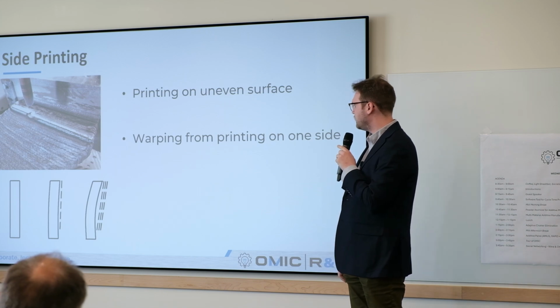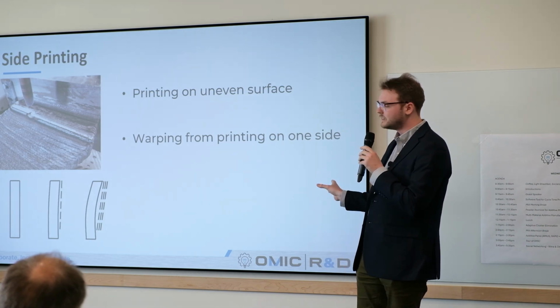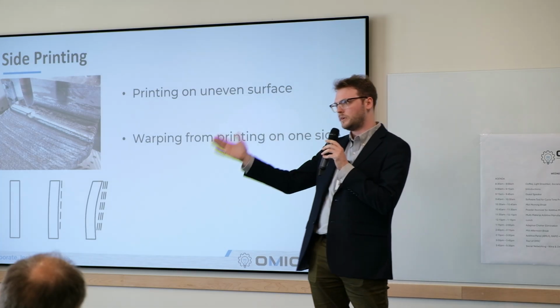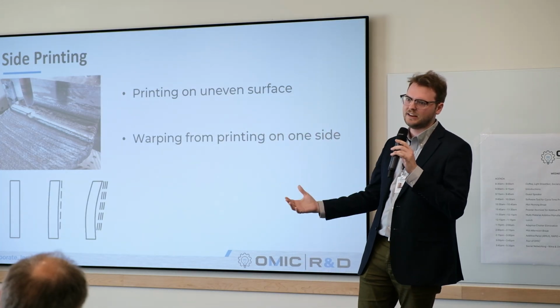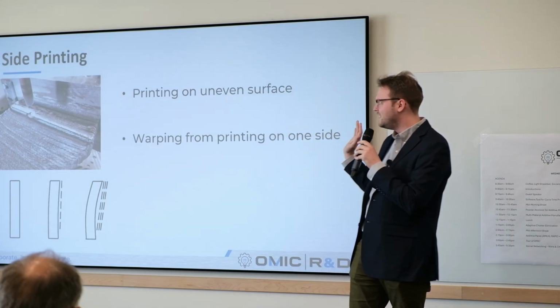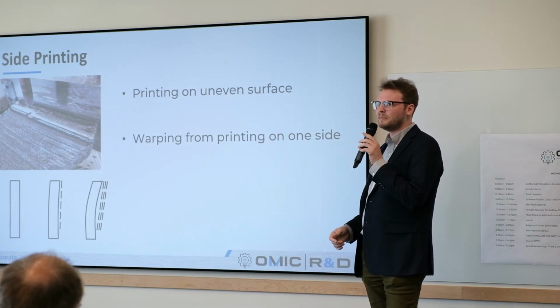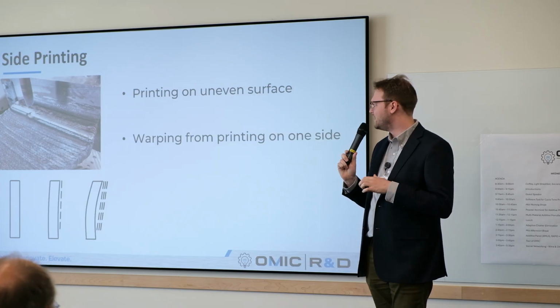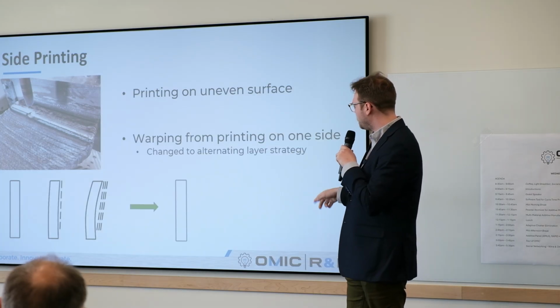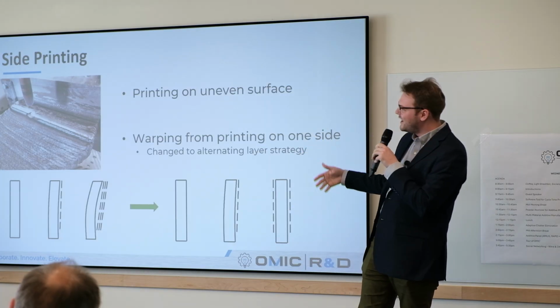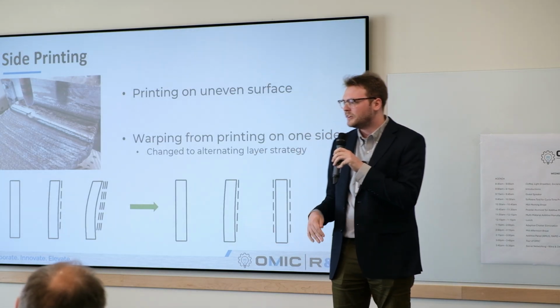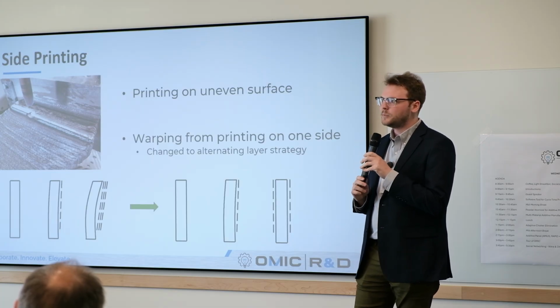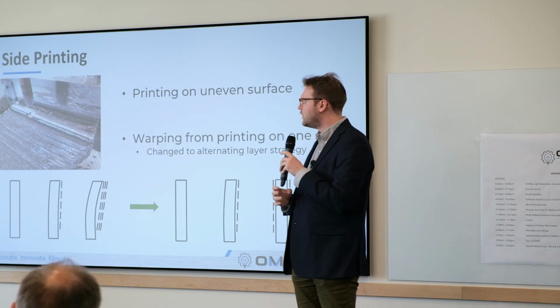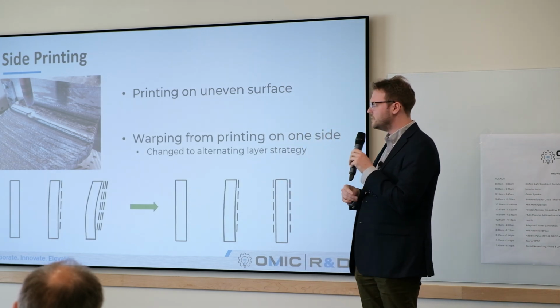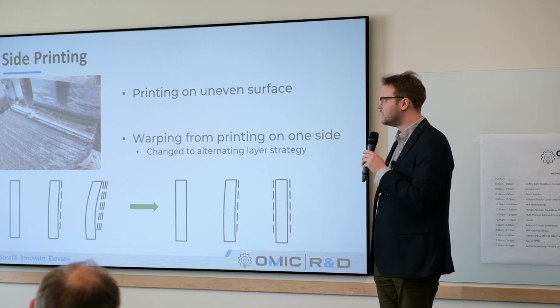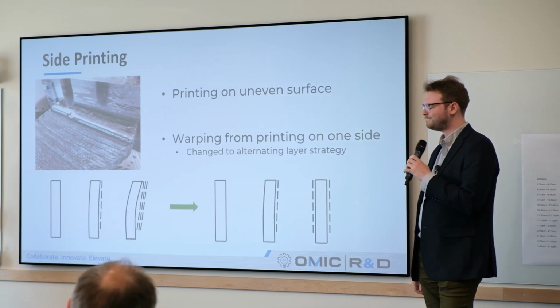And so instead, we take this approach that the 5-axis capabilities our machine offers, where we can print on one side and we can print on another, and we disperse the heat evenly. And you think, oh, this is intuitive, it's easy, you should always do that. But you have to mess up first and learn that that was not what you were supposed to do. Yes, glorious. So now we can print to an alternating strategy. And this allowed us to build our components much faster. We were laying down lots and lots of titanium. We're going through 45, 50 pounds of titanium wire in 10 hours. Mm-hmm. So we're cooking. Exactly.